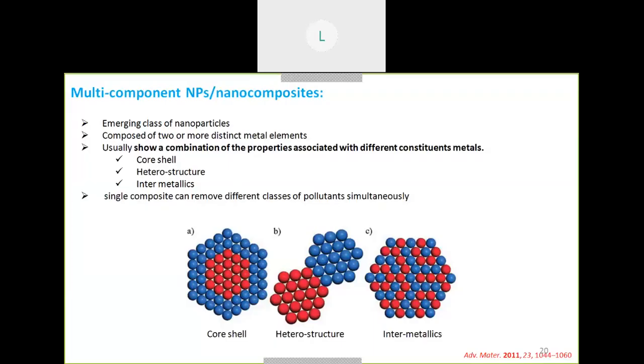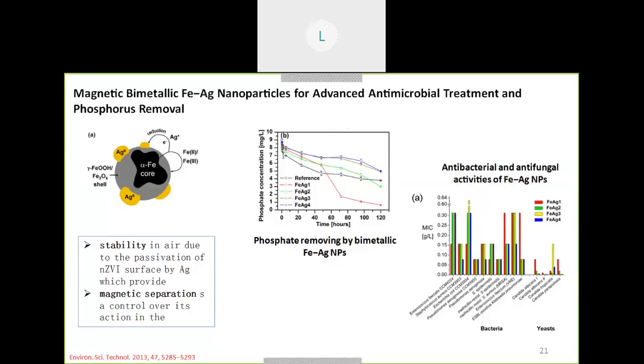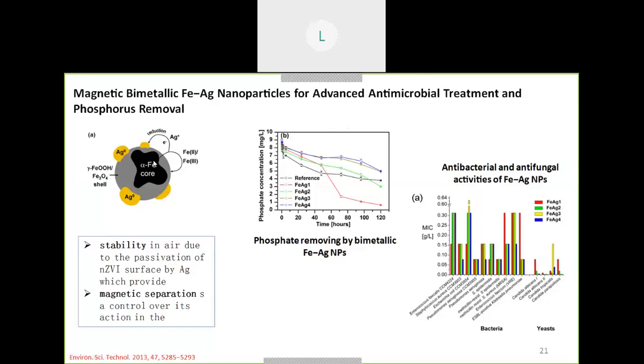On the basis of such processes, there was one paper in Environmental Science and Technology. They synthesized the bimetallic. You will find a lot of papers, but this catches the eye because of its multifunctional capacity, and they remove the phosphorus and show the antimicrobial activity of the material. What they did, they took the commercially synthesized nano zero valent iron, they dipped that into the AgNO3 solution. As the nano zero valent iron is very reactive, it tends to get oxidized or passivated. They give the electrons to the Ag+ ions, which then get reduced into Ag0. So this is how they form the bimetallic, which is a very easy technique. And the stability of this material was very high because the passivation was provided by this noble metal, which is not very reactive to the environment of the water.